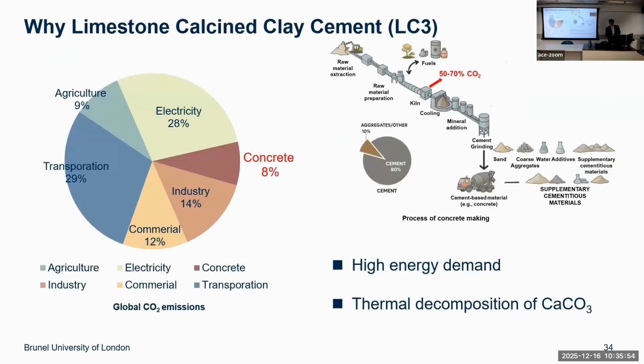Now today I want to talk about one piece of my work, which uses aqueous in-situ carbonation. Okay, and why we chose limestone calcined clay cement. One of our students will also use magnesium oxide cement. We have also done this one. So this student focuses on LC3. The main thing is we deal with clinker: in Portland cement you have 95% by weight clinker. The production of clinker generates quite a lot of carbon, so we're trying to use other ways to reduce the amount of clinker.